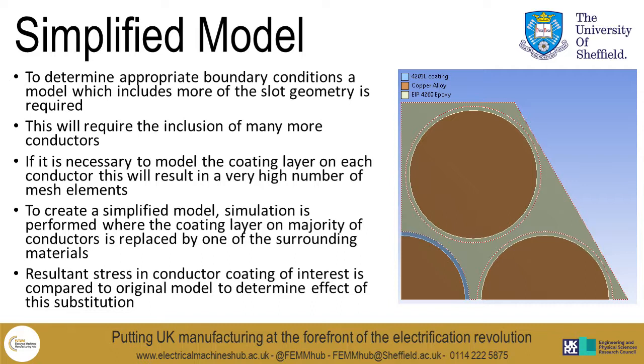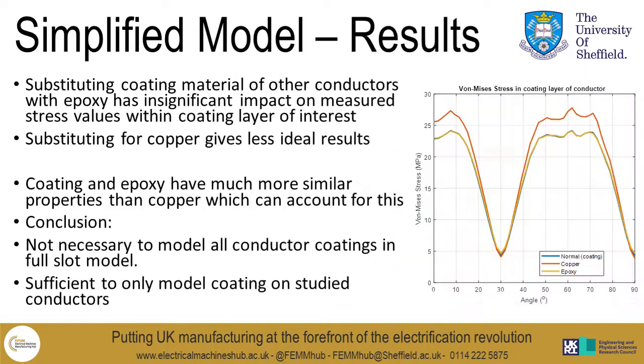As a result of this, what we wanted to see was, is it possible to omit the coating layer on conductors which are not the conductor which we're actually directly interested in. To try this, we used the model which is shown here, whereby we replace the coating layer with one of the surrounding materials, so in this case the epoxy, but we also tried replacing it with the copper to see how that affected the resultant stress on the conductor of interest.